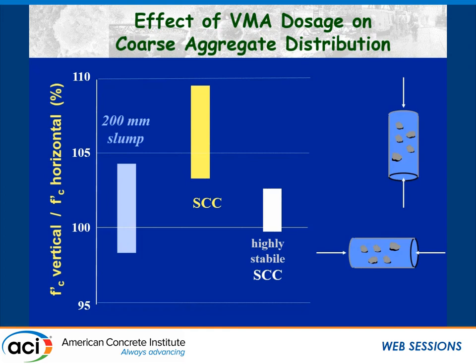And the reason for that, this is what is shown here. This is a vertical one, and these are the embedded aggregates, and underneath them in black is that accumulation of bleed water and settlement. When you apply a stress that is perpendicular to this weakness zone, it's compressing it. But if you were to apply it parallel to this weakness zone, line of forces are aligned and you have a lower apparent compressive strength. And we see over here with the highly stable concrete, this is much reduced. So you're almost taking an anisotropic material to an isotropic material.